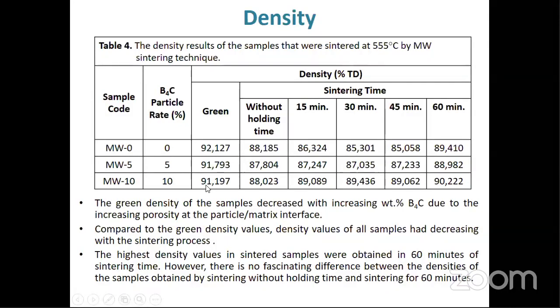Compared to the green density, the values of all samples had decreased with the sintering process. The highest density values in sintered samples were obtained in 60 minutes sintering time. However, there is no significant difference between densities of the samples obtained by sintering without holding time and sintering for 60 minutes.